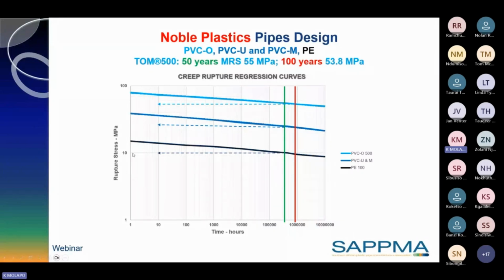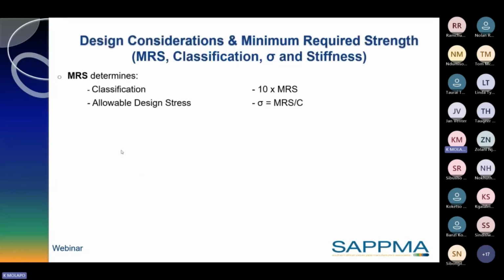So the way the classification works for these pipes, you take that value, which is the rupture stress, or the MRS, the minimum required strength, and then you multiply it by 10. I will show in the next slide what I actually mean. So here is the MRS as you are reading it from the previous graph, which is the value of 10, and then you multiply it by 10, you get 100. So for PE 100, this is how you get to that classification. In the past, we had a PE 80 and then PE 63. So the MRS for those two were 8 and 6.3 MPa.